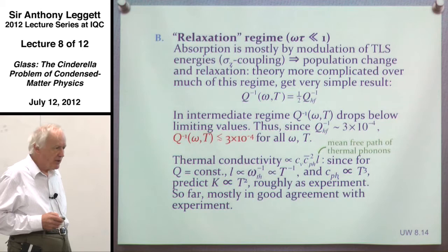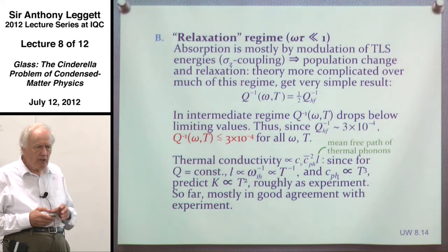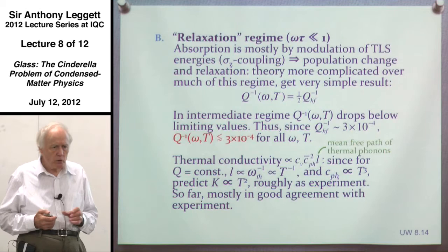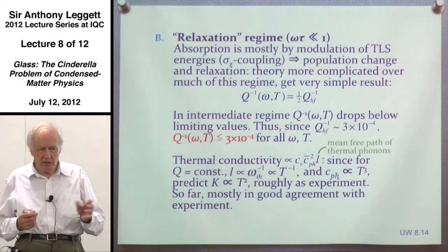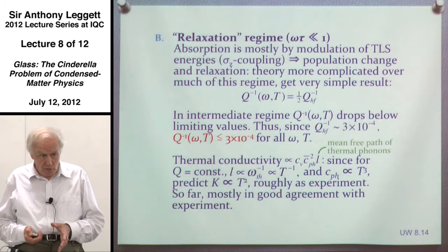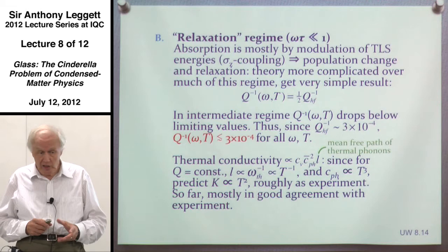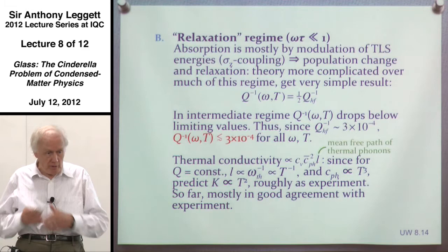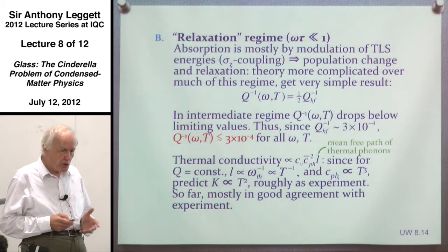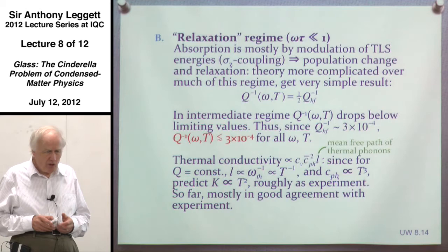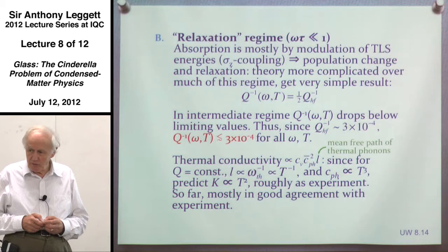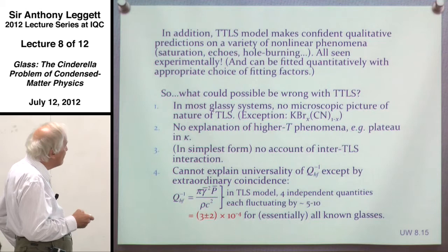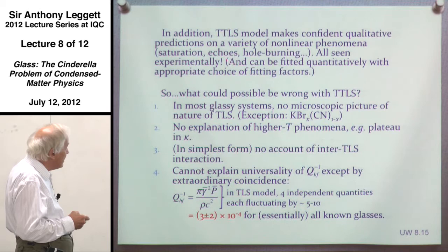There's one other qualitative feather in the cap of the TTLS model. As soon as this model was developed, people immediately started to realize that we have a lot of experience dealing with two-state systems in quantum optics and NMR. We can basically take over all that lore and predict all sorts of interesting nonlinear effects — saturation of the ultrasound absorption for sufficiently large amplitude, echoes, the so-called hole-burning effect, a whole gamut of things seen in quantum optics and NMR. These predictions were made ahead of time, and sure enough, they did turn out in the actual experiments. So at this point, the TTLS model appears to be doing pretty well.